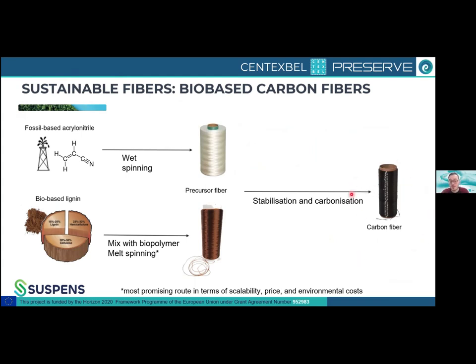So really the carbon fibers, and from that the composite materials from carbon fibers, is what is used right now, but we want to do it from a bio-based perspective. So by using bio-based lignin, which is widely available as well, and then making this precursor fiber from this bio-based lignin. Also, like I said, this is together with bio-based polyamide.